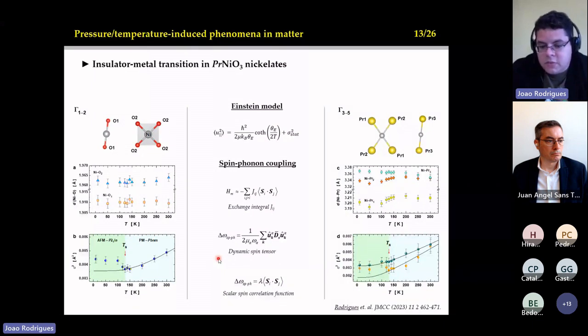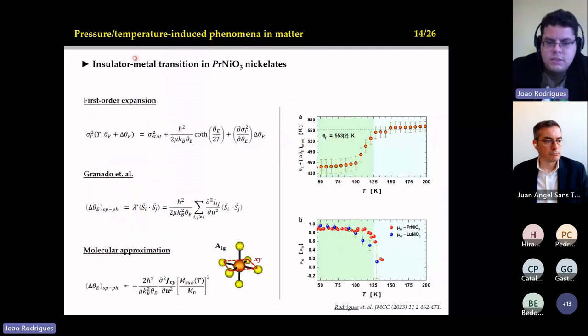So I'm talking about this because if I want to use this material for spintronics, I need to know very well what is happening with this kind of coupling. If I can use it, if I can transmit the information using spins or not, depends on how the spins are coupled with the phonons. Okay. And also we discovered that this spin-phonon coupling is very localized. It's very localized around the nickel-oxygen vibrations or surroundings. Okay, if you try to see this same effect for the outer shells, for example, at the level of the praseodymium-nickel interaction, which is around 3.32 angstrom, we cannot see this effect anymore. Okay, so the spin-phonon coupling is very localized. So this is how we managed to do this model, okay?